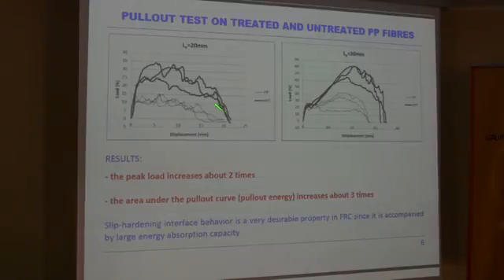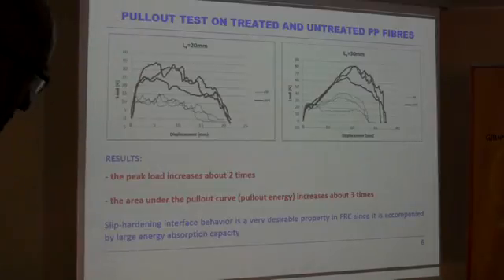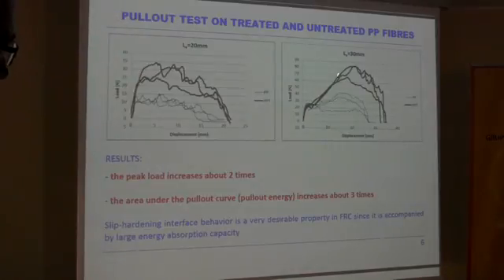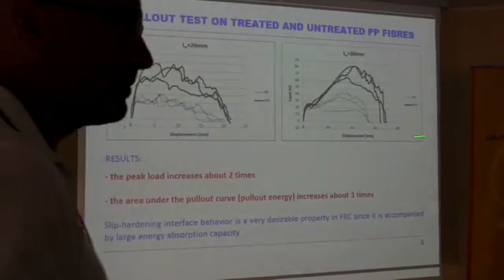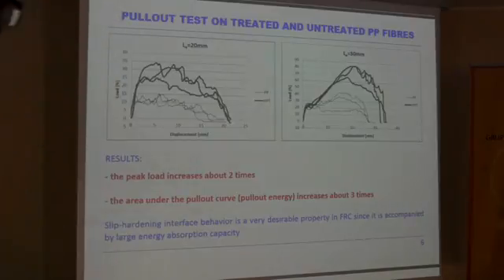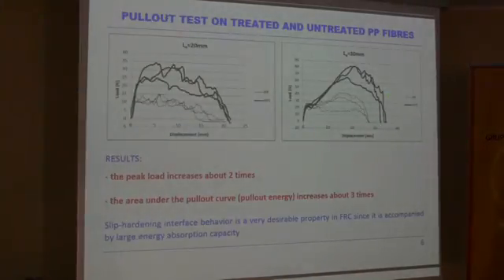Moreover, the area under the pull-out curves, which corresponds to the energy dissipated during the pull-out process, increased about 3 times between untreated and treated fibers. Therefore, we show that the treated fiber displays a remarkable slip hardening behavior of the bond strength. The bond strength increased remarkably with the slip, with the displacement of the fiber. And therefore, a slip hardening interface is a desirable property because it's accompanied by a large energy dissipation.